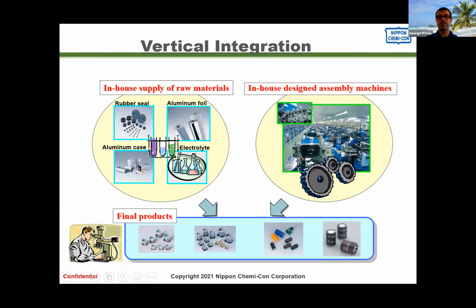I mentioned earlier about raw materials. And raw materials, especially the rubber seal, the foil, and the electrolyte are really the primary drivers of quality and long-term reliability. We are, if not the only one, one of a handful of suppliers that actually mix their own electrolyte. We buy the raw ingredients and then we mix it on site. And electrolyte tends to absorb water, tends to be very hygroscopic. So it's very, very important to consume the electrolyte within typically 2 or 3 days after it's mixed. Otherwise, it will start to basically degrade unless it's impregnated inside the element.